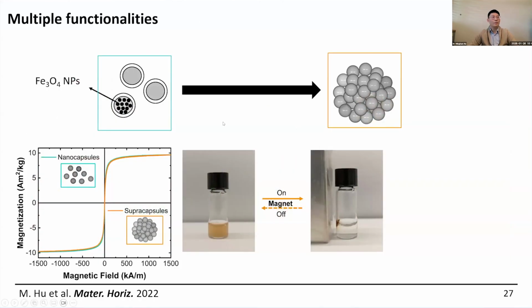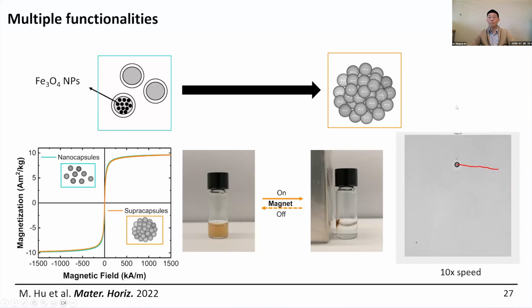And the next thing we do is we also encapsulate to include the controlled local motion function. We encapsulate the magnetic nanoparticles, iron oxide, inside the nanocapsules. Then we assemble these nanocapsules together to make the magnetic supercapsules. And we can nicely see they still maintain the same magnetic properties. And here what I show is we simply use the magnet to draw the triangle. And this is the single magnetic supercapsule. And here you can see my hand is still a little bit shaky.